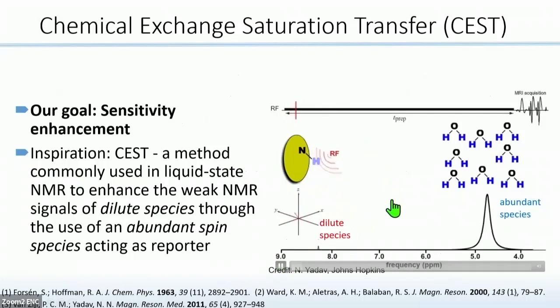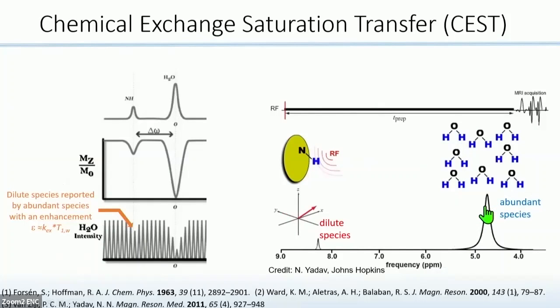And you can see in this nice animation, the way CEST works, you saturate the dilute species, and then by means of chemical exchange, you indirectly saturate the protons of the abundant species, and then you enhance your dilute species. So this is the type of spectra you usually achieve in CEST. They're called Z spectra. And it's essentially a mirror image of your regular spectrum, and your dilute species are enhanced in proportion to the exchange rate.